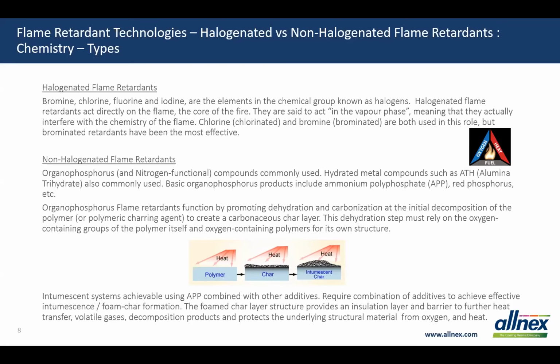For non-halogenated flame retardant technologies, again, it's a fairly broad overview here. There are a wide range of non-halogenated alternative flame retardants available today, and many are based on organophosphorus and nitrogen chemistries. However, other technologies also include hydrated metal compounds, and a common one is aluminum trihydrate, which has been used for many years. Not as effective. You need high loadings of ATH in general to get good reduction of flammability, but they do have very good low smoke properties, those sorts of filled composites. But there are other issues involving reduction of mechanical strength properties and other properties which are associated with those additives.